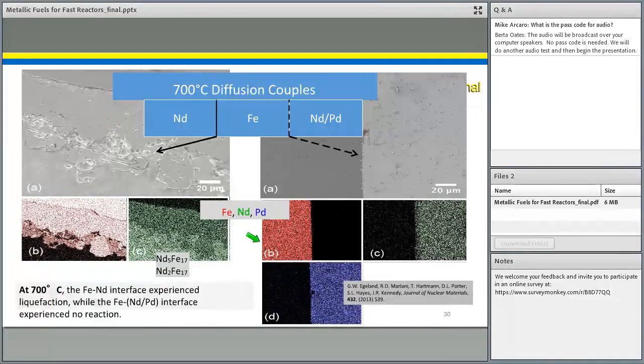We've also done a lot of out-of-pile diffusion couple work to look at this issue. So for instance, here's a diffusion couple of iron versus neodymium, pretty simple diffusion couple at 700 degrees C, and we held it, I believe, for 100 hours. And the interface of the couple is here, and what you see is not only extensive interaction between iron and neodymium, but at 700 C there was significant liquefaction of that interface. This is not unexpected. This is what would be expected.